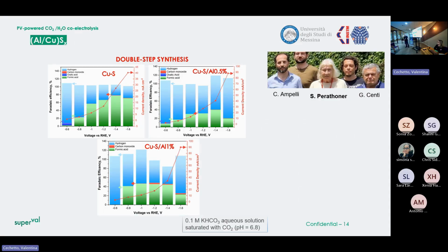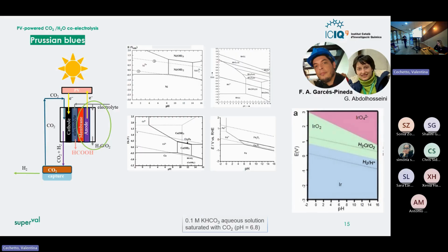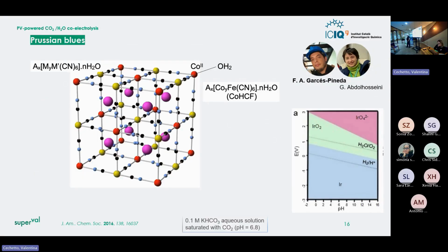So now we want to oxidize water, as I mentioned, and this is the work of Felipe Garces and Abdolhosseini at ICIQ. If you want to work with these conditions, you cannot use typical metals. Typically, for water oxidation, you are going to use metal oxides. In these conditions, pH 6, 7, most of the metals dissolve under an applied potential. So most of the devices use iridium oxide, which is expensive and scarce. So how can we solve this instability due to the pH of the metal? Well, instead of oxides, we may use coordination polymers. In this case, this is Prussian blue.